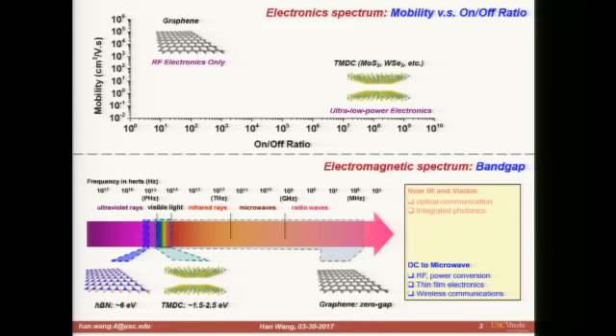But transistors based on these materials show very high on-off ratios, mainly because of two reasons. Firstly, the two-dimensional geometry of the channel allows excellent electrostatic control by the gate over the carrier flows in the channel, and also the band gap of this material is typically relatively large compared to materials like silicon. So that gives rise to a high on-off ratio in these transistors.